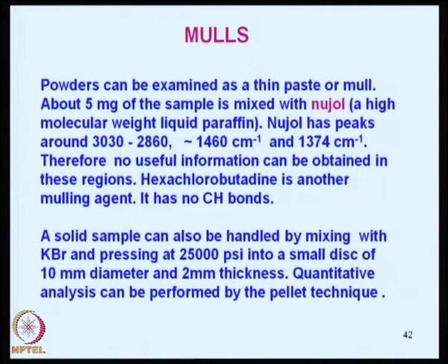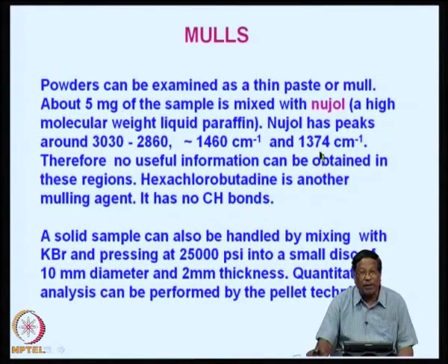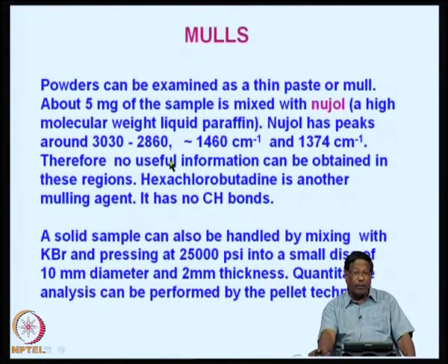Now, you can imagine that NUJOL being a paraffin, it will have carbon hydrogen bonds, mostly saturated carbon hydrogen bonds. So, when you take a powder, you have to subtract the peaks from NUJOL. NUJOL has peaks around 3030, 2860, 1460 and 1374 centimeters inverse. So, these are the NUJOL peaks which you will have to discount when you are taking IR spectrum of the samples. Therefore, basically you cannot get any useful information about a compound which contains NUJOL in these regions, that is 3030, 2860, around 1460 and 1374. In other regions, it is useful.